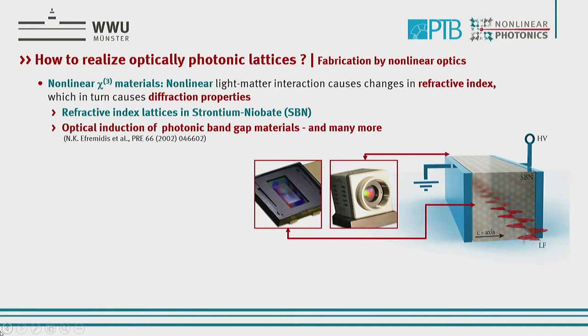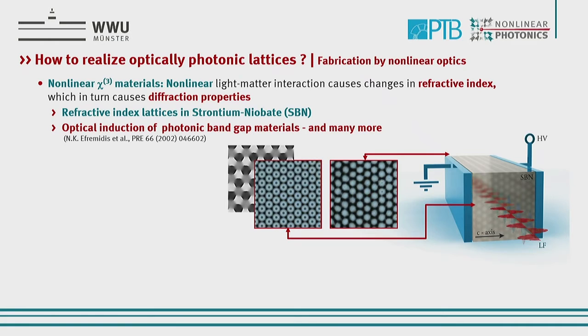So how do we do that? On a first glance, we have a material that is sensitive to change the refractive index by light. This is, for example, here a strontium barium niobate, as it is here. And now what we do is we have a spatial light modulator that impinges laser light onto it and then modulates it in a certain way to create, for example, such a hexagon structure. And we shine this hexagon structure onto the material. If we have these wave vectors being on a circle of the same length, then we get a beam that during propagation does not change, and so thus the refractive index that is created. And by a camera, we can monitor that. And then we can create, for example, here, by the inset, by a phase and an amplitude, a hexagonal structure. So then we have here a refractive index that is not changing during propagation for a length of that material,